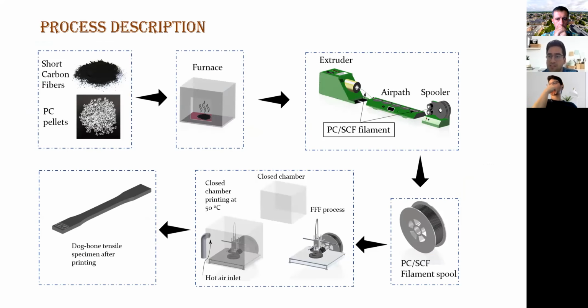Now, the process description. I already discussed some portion of this process before, but I will give you the overview one more time. We take two different materials. You can take two different polymers as well, or any polymer and a reinforcement in the form of fibers or powders. Then we dry them, then we shift them to the extruder and convert the material into filament form, because most 3D printing technologies use filament as a raw material. So you have to convert the pellets, powder or fiber into filament form. We create the composite filament with the help of an extruder, then we spool it, then we transfer it to the 3D printer, and then we do the 3D printing of the composite structures. So this is the entire process.